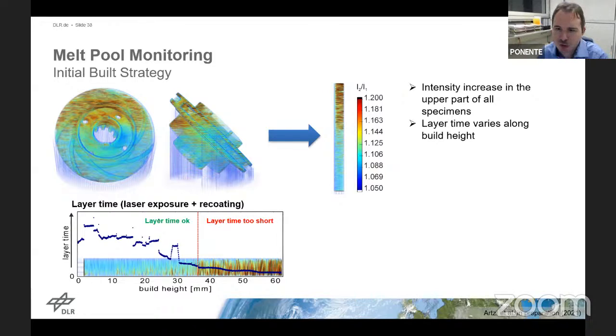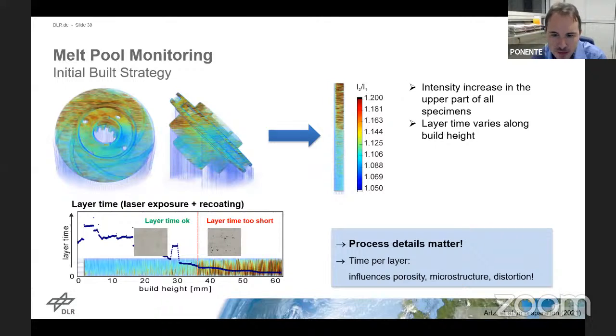So with such a large part and such a large layer time, this intrinsic heat treatment parameter that we developed on the small coupons is actually no longer effective. So you have to really look for small effects like the processing time per layer. If you change, for instance, the number of parts on a base plate during a build and make one build with a single impeller and one build with 6 impellers on them, the material properties will be different between those. And this is simply a time effect in this case. So it's kind of an indirect effect that's quite understandable and not very surprising when you think about it in the end. But we were surprised during our studies how much influence this actually does have.